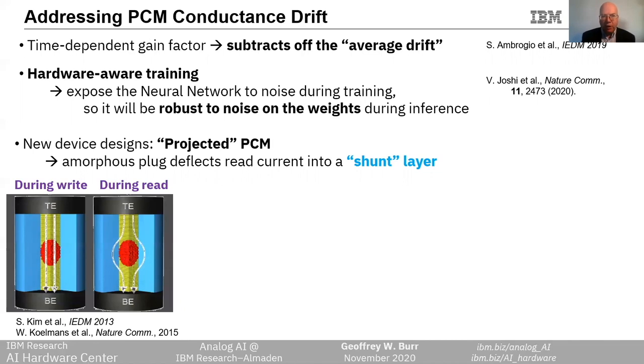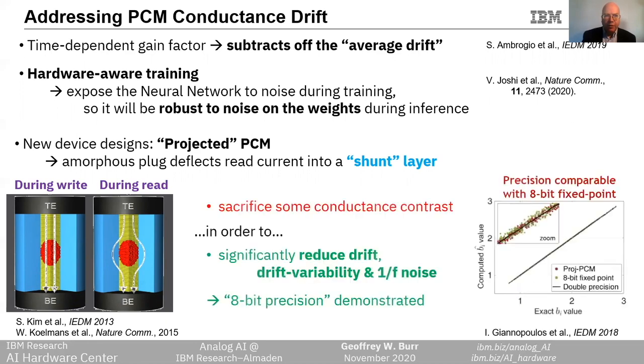We have been working for quite some time on new PCM device designs. In a projected PCM device, the amorphous plug doesn't block read current so much as deflect it into an intentionally included shunt layer. This sacrifices some of the huge conductance contrast in our devices, but in exchange we get significantly lower drift, lower drift variability, and lower random telegraph noise. We have been able to use these devices to achieve matrix operations at an effective precision equivalent to 8-bit fixed point. So we're very excited and optimistic about the combination of all these techniques for inference.